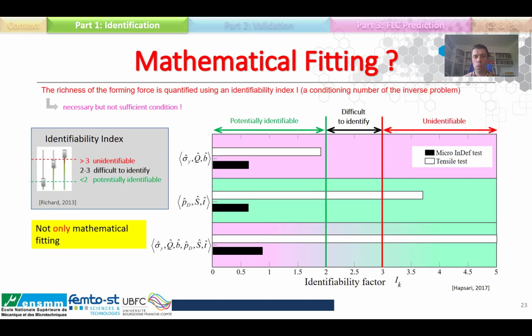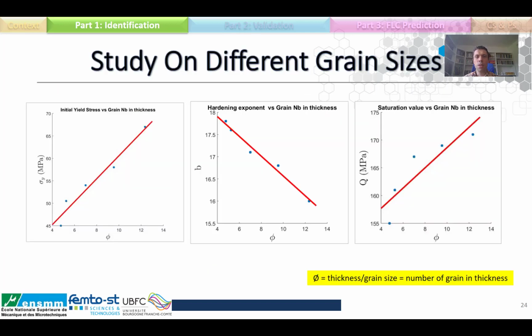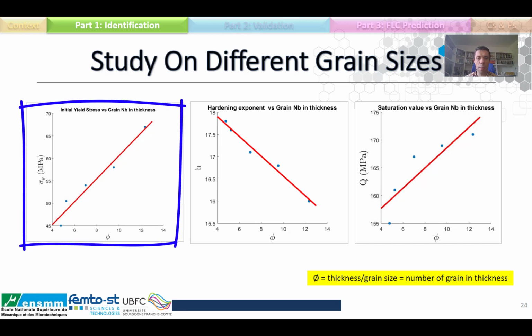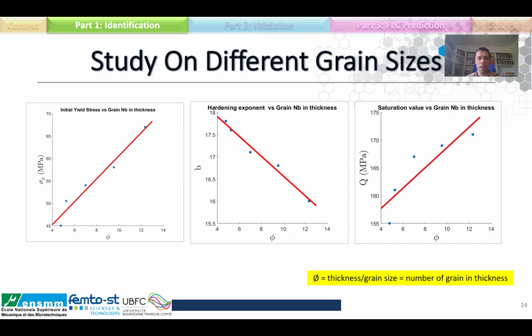I don't have time and I don't want to develop some mathematical calculation here, but we can just note that the identifiability index is based on the calculation of the Jacobian matrix. This study has also been realized on different grain sizes, which means that we use different phi ratios. And with the Micro InDef test, we obtain a set of parameters for each grain size. Evolution of some parameters on phi is represented with this image. For initial yield stress, we found a typical Hall-Petch type law, which means that the elastic limit has a variation with the inverse square root of the grain diameter.